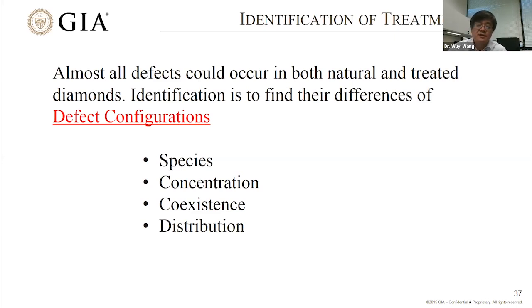How do we separate naturally colored diamond from these treated ones? Basically, we heavily rely again on the defects. It would be very easy if we could find some defects that only occur in either natural or in treated. That would be very easy for us to do. Actually, it is much more challenging than that. Almost all defects could occur in both natural and treated stones, so there's no simple way to separate these two groups. We basically rely upon the defect configurations in a diamond, that would include the species, like what type of defects occur in a diamond, their concentration, their coexistence, what stays together, and their distribution. Distribution is very important as well.